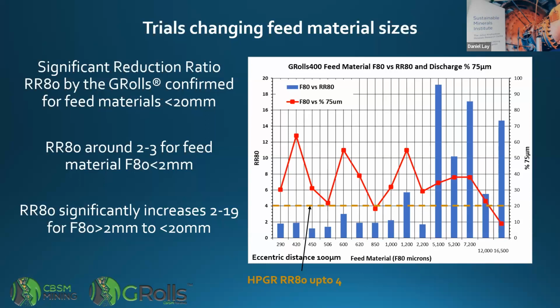efficient. And as you can see, even when we get really coarse material, the fines generation is quite high. These peaks and troughs are probably because of different hardness of the material, but you can still see getting quite high percentages of fine material.